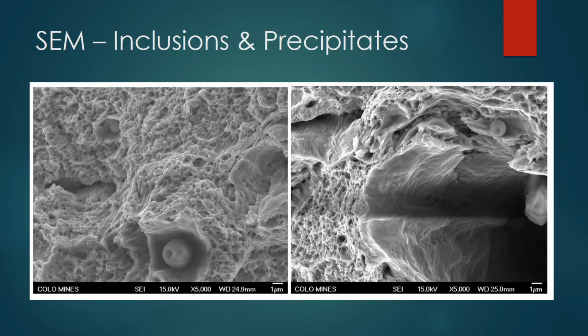Here we have images of inclusions and precipitates for the additive manufactured sample. On the left image, we see spherical precipitates, or oxides. And these sit in very smooth-walled cavities, which indicate brittle fracture. On the right, we see inclusions, which are actually causing rastering in the image because it's non-conductive. So it gets saturated with all the electrons being shot at it and won't let any more pass through it.